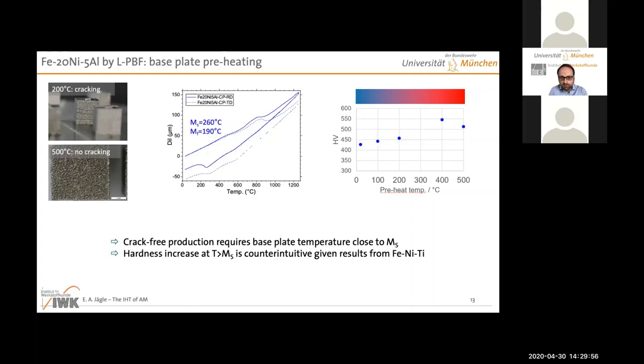But we also looked at the hardness and we saw that at 500 degrees, there's definitely a higher hardness, by more than 100 HV, than in the case of no preheating or low preheating below the martensite start temperature. And at first glance, that makes sense, right? I mean, high temperature precipitation, sure. 500 degrees is actually a reasonable aging temperature for this material. So that is not really a problem.